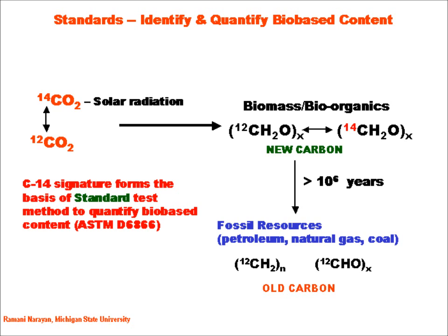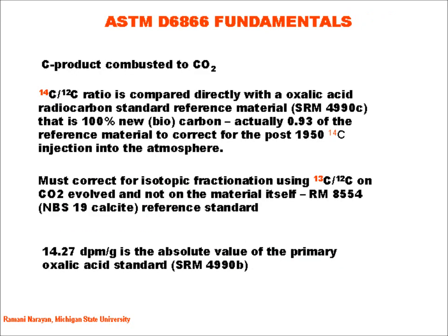And we have now codified this into an ASTM standard, ASTM D6866, and the carbon-14 signature forms the basis of it. So I'll take the product and I'll talk about it in a minute, but new carbon versus old carbon. The fossil carbon will have no radioactive carbon signature associated with it, and the biocarbon will have a radioactive signature associated with it. So, some fundamentals.